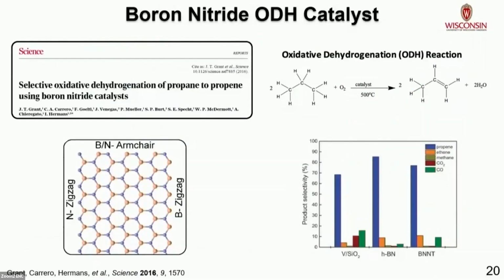Now, the next system that I'm going to show you is what really motivated us to perform these experiments. And this is looking at these boron-based oxidative dehydrogenation catalysts. So in 2016, the group of Hermans demonstrated that bulk hexagonal boron nitride is highly selective for the oxidative dehydrogenation of propane to propylene, and that it significantly outperforms the previous state-of-the-art catalyst, which was vanadium oxide supported on silica. We can see there's very minimal over-oxidation with boron nitride.